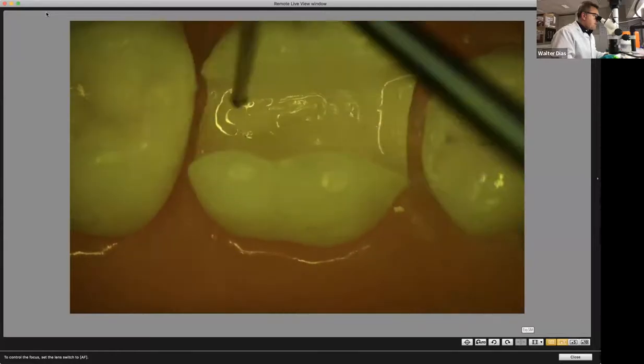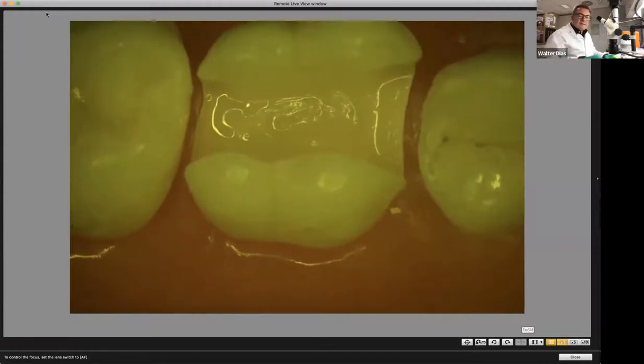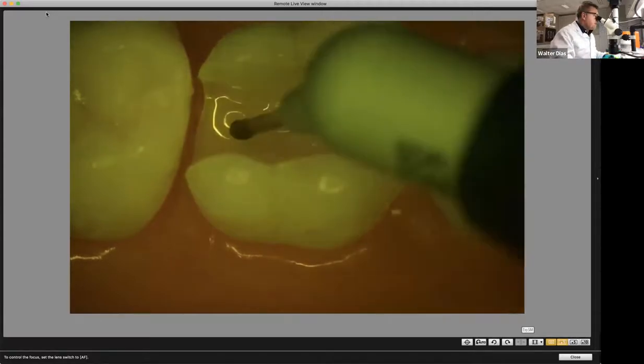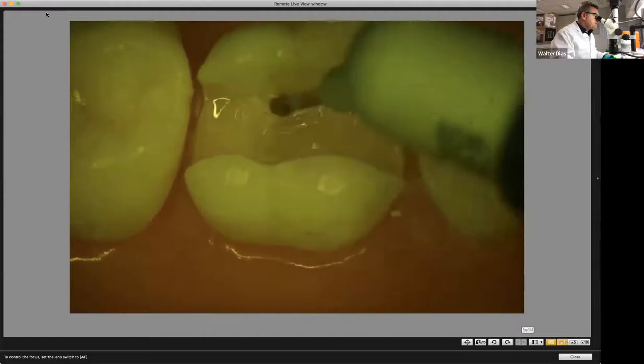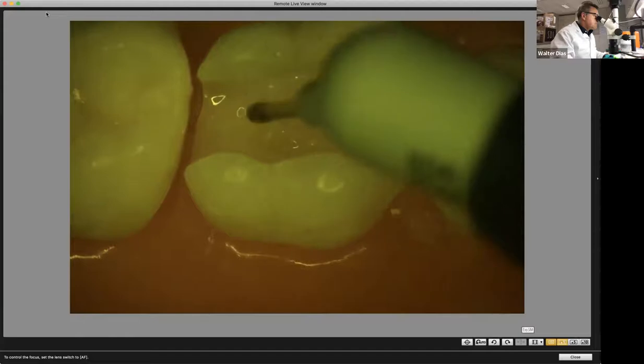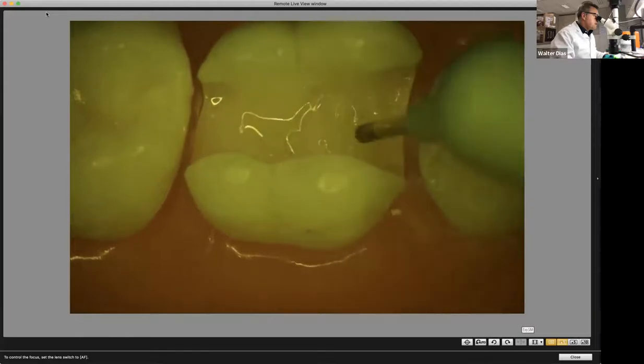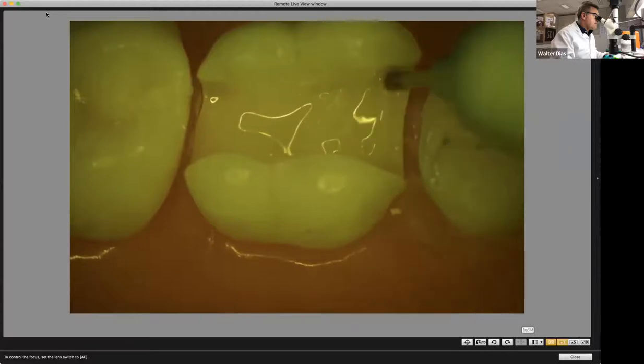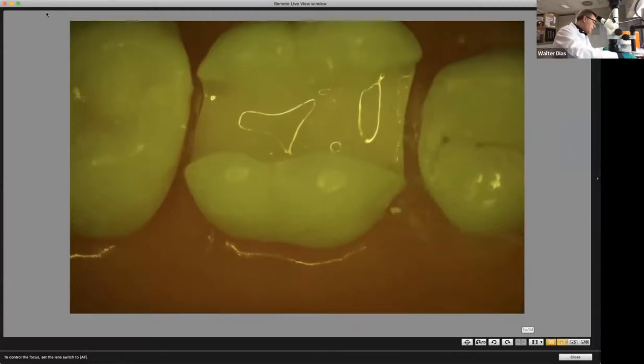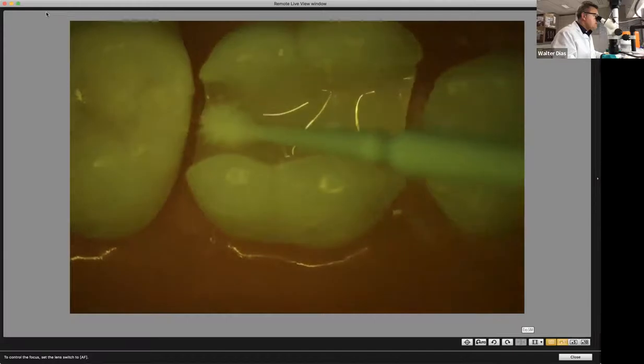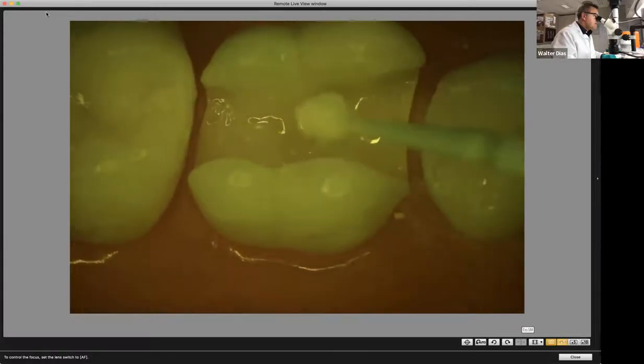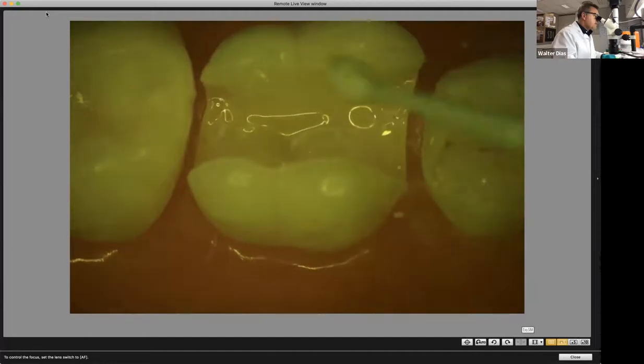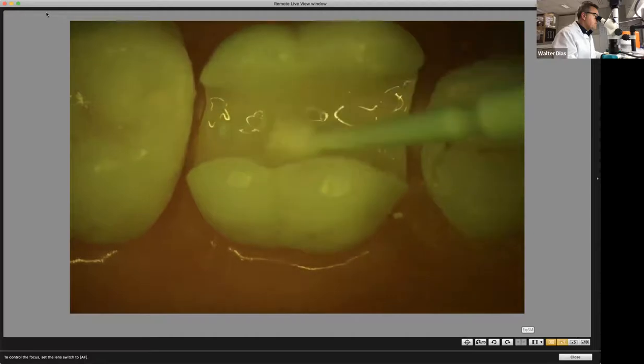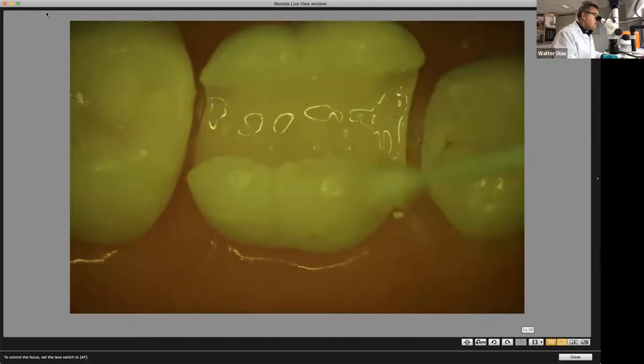Okay. At this point you can tack cure if you think that the material is gonna flow. You can simply tack cure it for 2 seconds, yeah. But I'm just gonna continue a little bit. This is a kind of a thin layer. And now with a very gentle motion using a micro brush, you can pull SDR towards the margins. Okay, like this. And this is where this material is magical because you cannot do this with the flowable, man. And then at this point, I think I'm getting very good results.